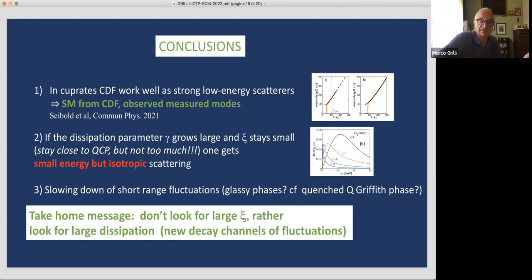Now the question is, what happens if we want to extend this linear behavior down to the lowest temperatures, as it occurs when you apply a strong magnetic field? Then we need the Landau damping parameter gamma to grow larger and larger. And in this way, one can keep xi finite, so the correlation length is finite. So the idea is that we stay close to the quantum critical point, but not too close. And still we can get, thanks to a diverging gamma, a smaller and smaller energy.